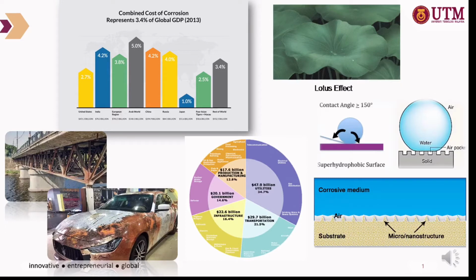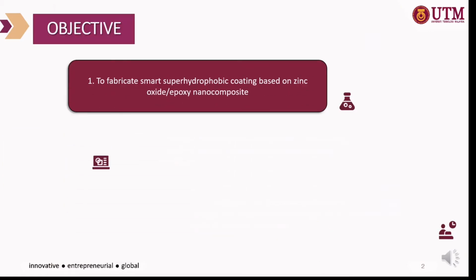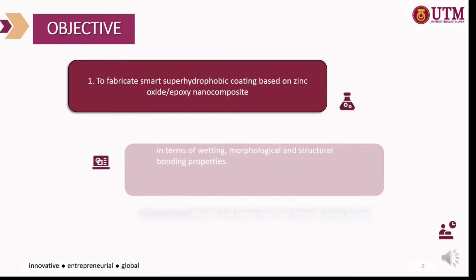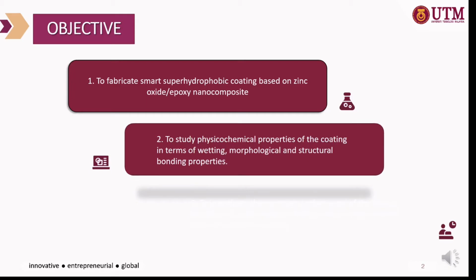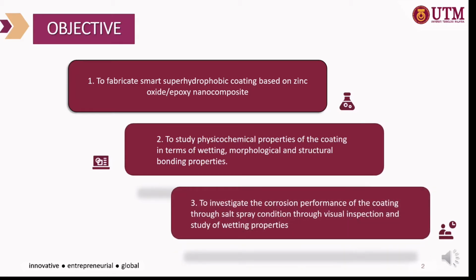Until recently, corrosion protection could be efficiently performed using a superhydrophobic coating, but most studies either use complicated methods or expensive composition. Therefore, this study explores an unconventional fabrication technique for a smart superhydrophobic coating via zinc oxide nanoparticles with a simple and inexpensive method. To achieve superhydrophobicity, physiochemical properties of the coating are studied in terms of wetting, morphology, and structural bonding properties. Furthermore, corrosion performance of the coating is investigated through salt spray condition, through visual inspection and study of wetting properties.